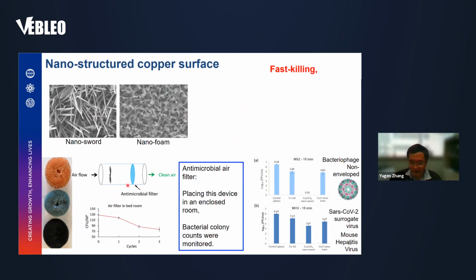And showing here is some results. So firstly, we have these copper foam balls, and we treat them to form this nanostructure, and then we put them in this air chamber for airflow to pass through. And we place this device in an enclosed room, and then we let the airflow go through these chambers. And you can see after several cycles, the bacterial content in the room keeps dropping. It really has played the role of an antimicrobial filter.